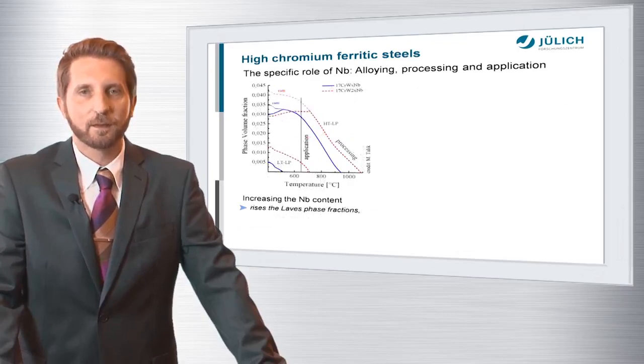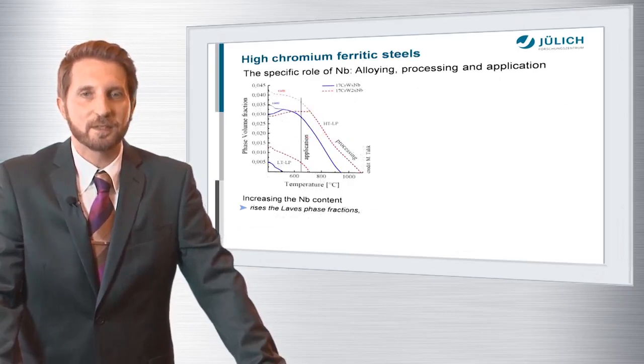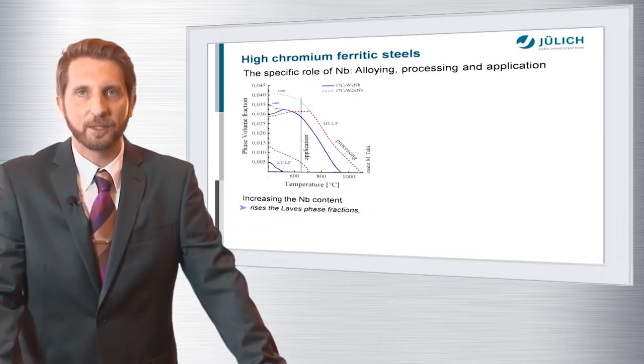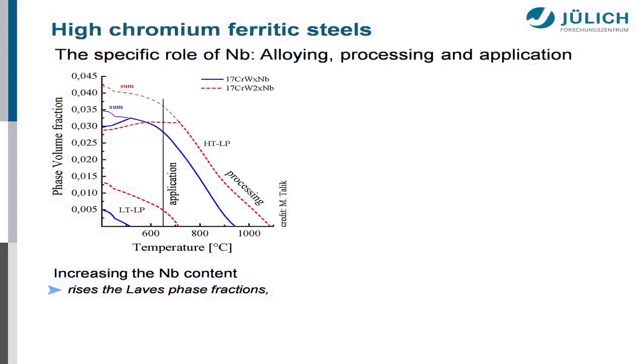Furthermore, doubling or increasing the niobium content does not only have a direct impact on application, it does have a direct impact on processing too, and this is depicted here in that graph. Again, the color code is the same. Blue is the base composition, red is the composition with doubled niobium content, and you can see that on the high temperature end, the dissolution temperature shifts by approximately 100 degrees C, and this does not only lead to higher long-term stability, this for sure means we have to change the process if you go for rolling or forging of these materials.